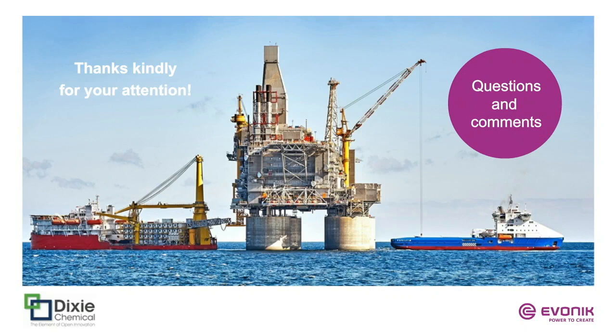Yeah, I agree. This is Boris, and I'd like to add for the audience also that this type of chemistry involving epoxy and anhydride cure is quite versatile in that you can really design different types of processing windows. You know, these can be very rapidly cured. These can go out to minutes or hours if necessary. But for mass casting of syntactic foams, if you're looking at deeper depths or thicker materials where exotherm is an issue, this type of curing chemistry really works very well to that and minimizes exotherm and improves dimensional stability of the castings.